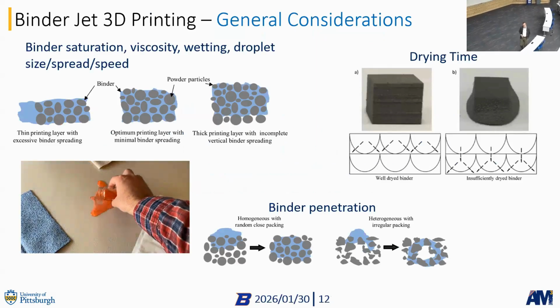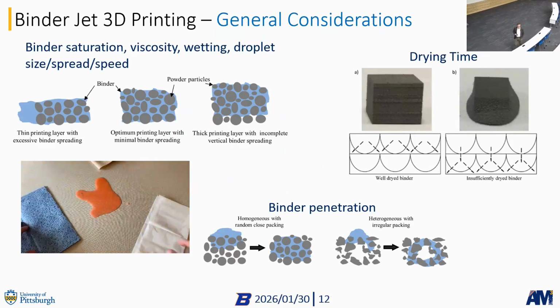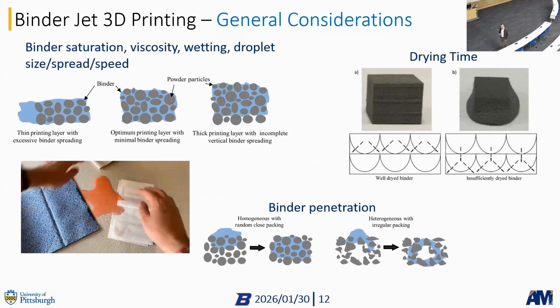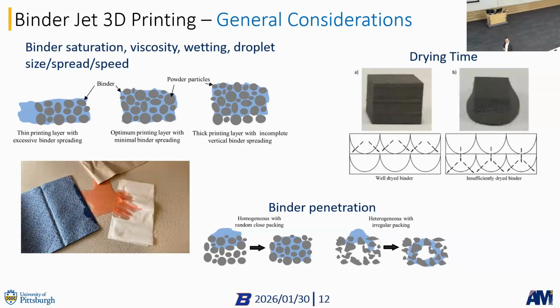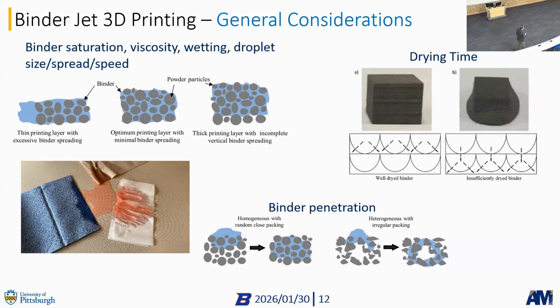So there's a lot that needs to be still considered. Doing binder jet 3D printing, we have an interaction between the powder particles and the binder that you're using to glue these powder particles together. And if you look here at this little video that I took, you see this is basically a binder, right? And here we have different cellulose that you can think of as different powders. Okay. What you can see is the binder is seeping into one of these much more than in the other two. And that is the same in actually powder, right?